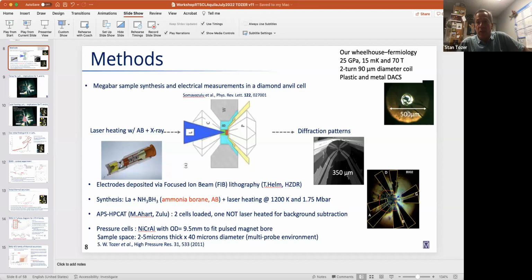But our starting point was, I show here a micrograph looking through a diamond anvil cell. This is extremely large culets, 540 micron culets. But this is work that Audrey did on the fermiology of YBCO when we pushed into the overdoped state of YBCO to look at the fermiology in this material. And she was successful in seeing quantum oscillations up to 25 GPa. But unfortunately, we didn't see any type of reconstruction of the Fermi surface. Or fortunately, because it flies in the face of what has been proposed.